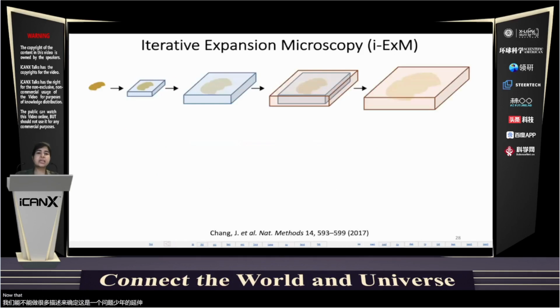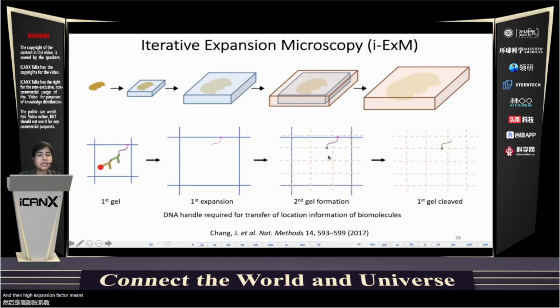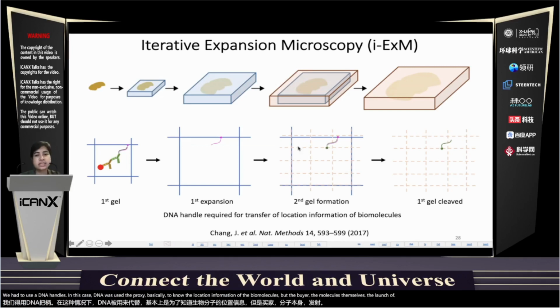Now we can think that we can also do this process iteratively. That is, after the first round of expansion, we can iteratively expand again, and then we can get a higher expansion factor. And a higher expansion factor means that we can get higher resolution. In the first round of this iterative expansion microscopy, which we call IEXM, we had to use DNA handles. In this case, DNA was used as a proxy, basically, to know the location information of the biomolecules, but the biomolecules themselves were lost after the expansion.